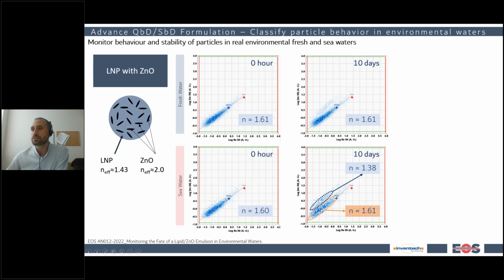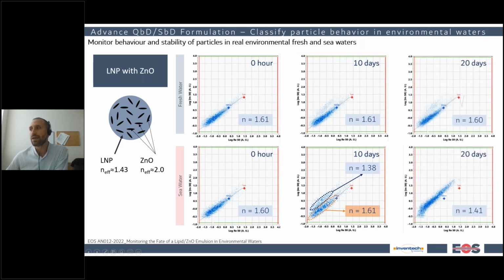But the particles in seawater start to change, and their change is complete after 20 days. They shift the position of the clouds toward an area corresponding to lower refractive indexes, while on the other side, the particles dispersed in fresh water are stable.